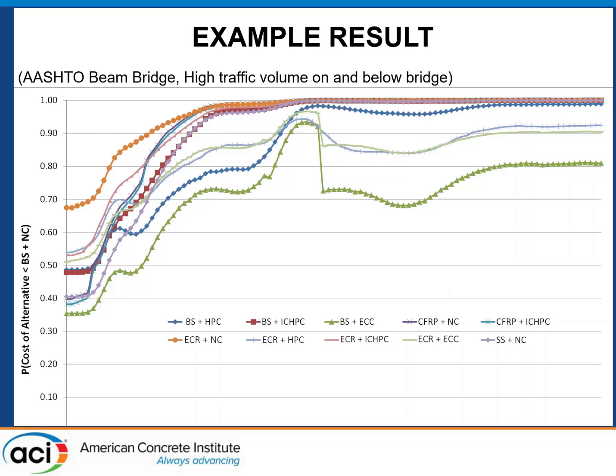And as you can see, some of these, mostly towards the bottom there, have a probability less than 0.5 or lower than 50%. In other words, it's likely they're going to cost more than the baseline. But some of our cases actually had, for the initial construction, a higher probability than 0.5 of costing less than the baseline. Now, the reason for that is the use of epoxy-coated bars in place of unprotected steel. The unprotected steel, at least with Michigan DOT, is associated with a cathodic protection system, and that's a significant initial cost of the bridge. When you eliminate that cost, that causes those probabilities to change quite significantly in some cases.